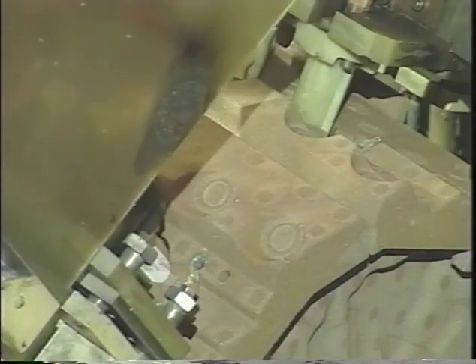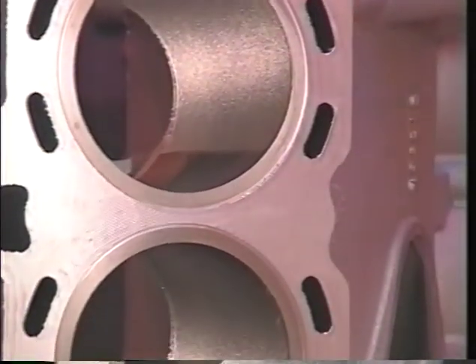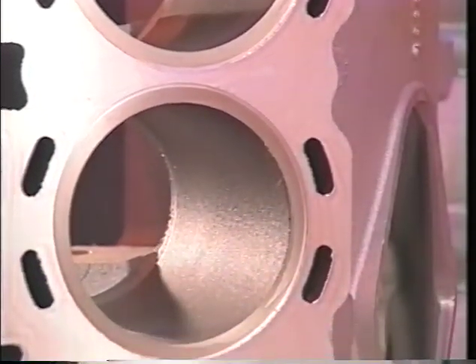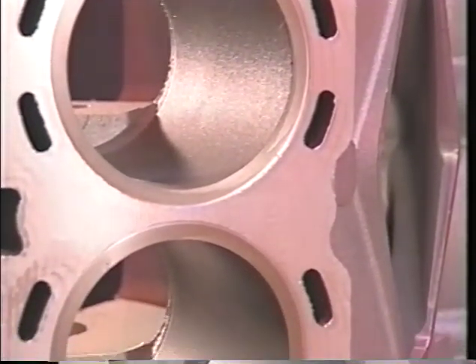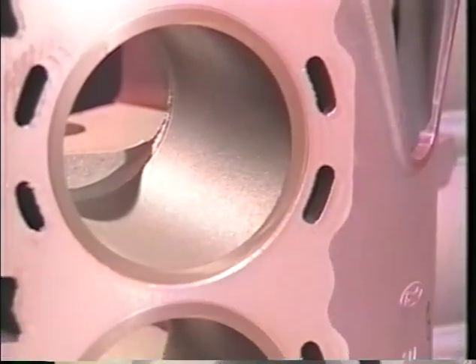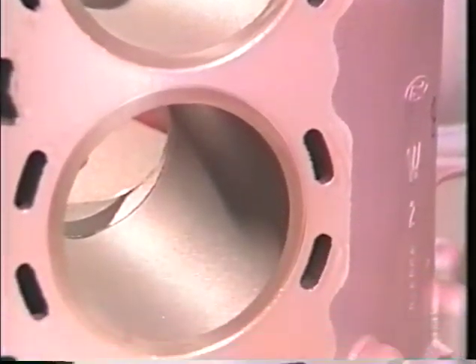Induction heater coils are inserted into the core package. This heats the cylinder liners to a temperature which ensures that a secure bond is formed when the liquid metal is poured and cools. Cast-in liners have a much more consistent bond than traditional force-fit liners. This process ensures complete adhesion of the aluminum to the iron liner.